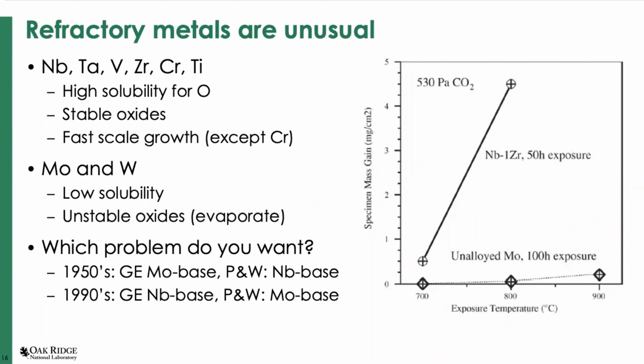I don't have as many results, frankly, with refractory metals. Haven't worked in that space in a long time, but there are some unusual things, and perhaps you know this, that the majority of refractory metals have a high solubility for oxygen, and they do form stable oxides, but they tend to grow really fast. Here's an example, the specimen mass gain at different temperatures. Nb-1Zr compared to moly get very thick oxides forming on the Nb-1Zr. This is actually an experiment to simulate the Mars environment.